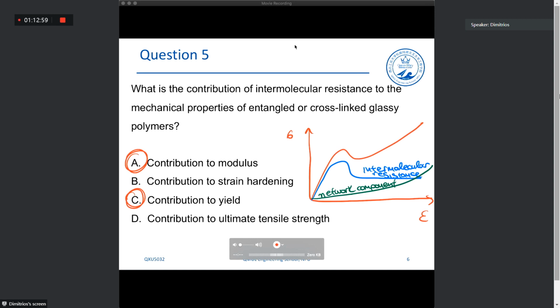As you can see, the network component corresponds to contributions regarding strain hardening and ultimate tensile strength, because essentially it provides the ultimate elongation and the ultimate strain hardening, while the intermolecular resistance contributes to the original part here, which is the modulus, and also here, which is, let's say, the threshold for plastic deformation. Okay.